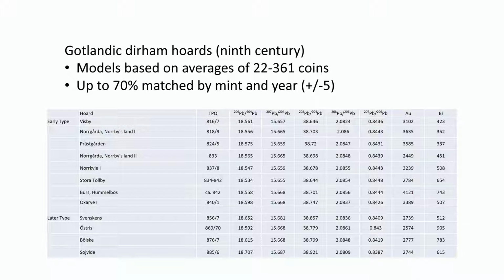And so we're able now to create a homogenization. So if you have an entire dirham hoard, you melt it into one object. This is the composition that you would get. And we can do that now with isotopes and also with elemental compositions. So with the gold and bismuth, these are the ranges that we would expect for recycled Islamic silver.